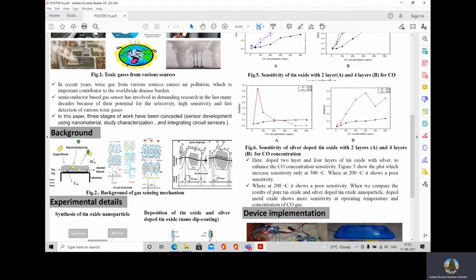When the Schottky barrier is high, there will be no enhancement of sensitivity. During reducing gases like CO, the Schottky barrier will be reduced, so the electrons can flow freely, so that we can measure the sensitivity to carbon monoxide gas or any other hazardous gas.